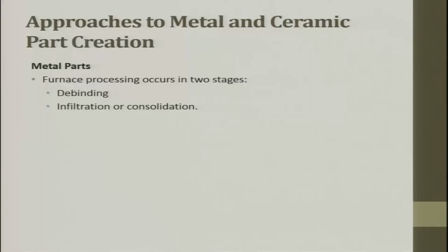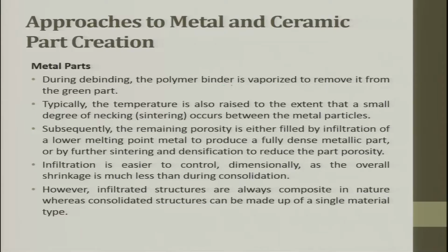The metal parts furnace processing occurs in 2 stages, one is debinding and the other is infiltration or consolidation. During debinding, the polymer binder is vaporized to remove it from the green part. Typically, the temperature is also raised to the extent that a small degree of necking occurs between the metal particles. Subsequently, the remaining porosity is either filled by infiltration of a lower melting point metal to produce a fully dense metallic part, or by further sintering and densification to reduce the part porosity. This is very important. If you are happy with the porosity, live with it. If you are not happy, you try to infiltrate material.